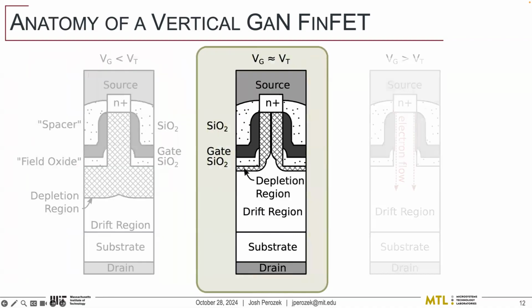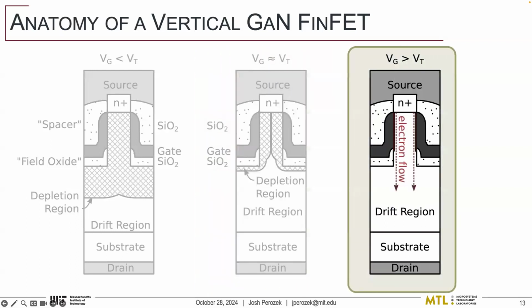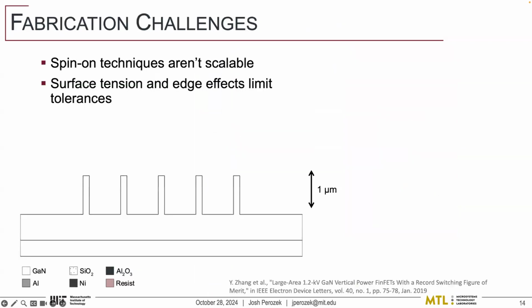As we increase the voltage on the gate, that depletion region formed within the fin shrinks until a narrow channel starts to form in the middle. That's the onset of threshold, and our device starts to conduct some current. And if we keep driving that gate voltage more positive, there's an accumulation layer that forms along the sidewall of this fin, allowing electrons to flow very freely, and now we're in the on state. So relatively straightforward in how they work. How we make them is a little bit harder.